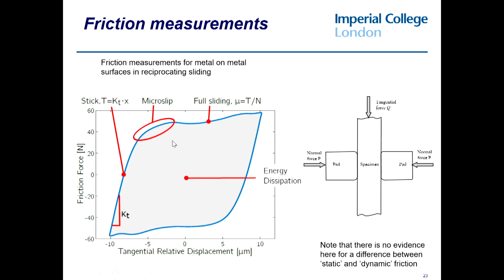And indeed, the kind of tests that we like to do, which are more representative, is to slide the contact a small amount in each direction. So we, in effect, take, say, a specimen, grip it with some pads, and we move the two relative to each other. And the kind of thing that you get is this kind of curve, and it's got some interesting features. The first thing that you can see is that you've got a region between here and here where there's sliding at an approximately constant force. And that's the region where we have Coulomb friction or Amontons friction taking place. But you'll see here it's only approximately constant.